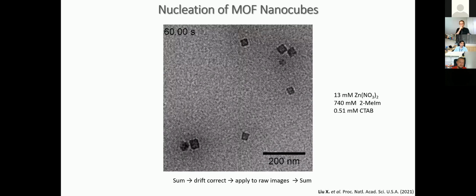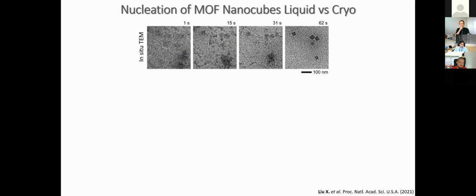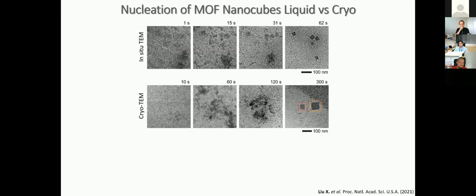So what we do is we take our in situ TEM images where we see homogeneous solution, phase separation, formation of amorphous particles, which then collapse into the MOF crystals. And we compare it with the quench and look approach of the cryo-TEM. So we take a reaction solution and we quench it at different times, and we observe the process, and we see, okay, more or less we find similar trends. Of course we had to do many of those to convince ourselves. This is all in the supplementary information, but it's not just one shot where you handpick the one that you like. You have to really convince yourself that what you're seeing is relevant. And so I told you that the last stage is crystallization. This stage and this stage is not crystallization. But how can I tell from here?